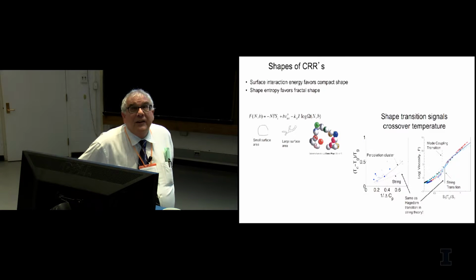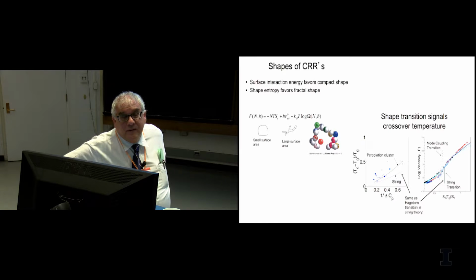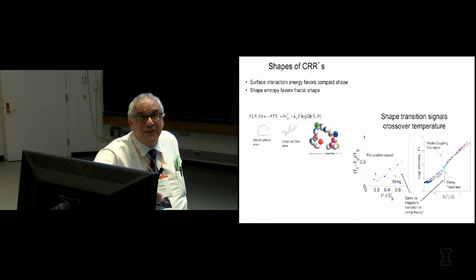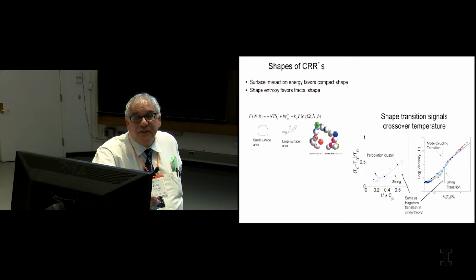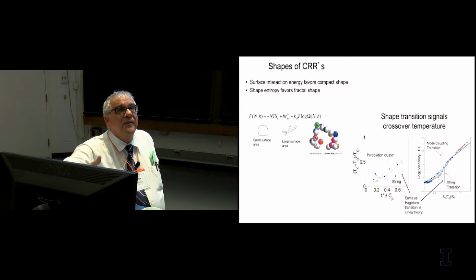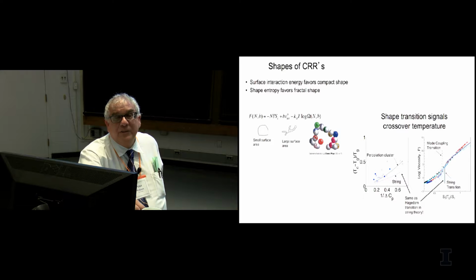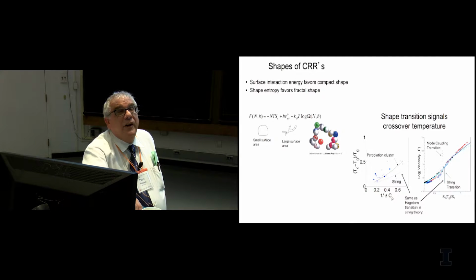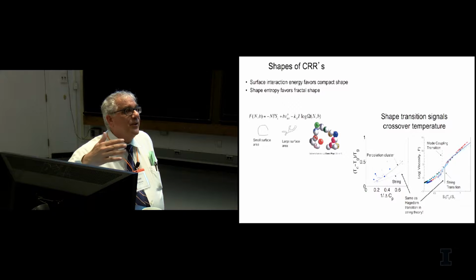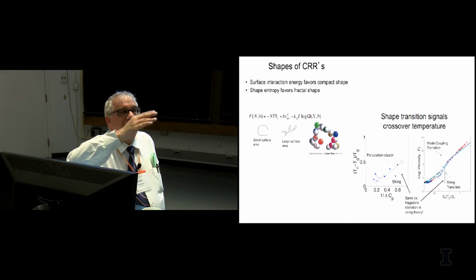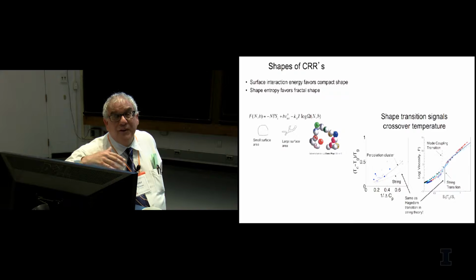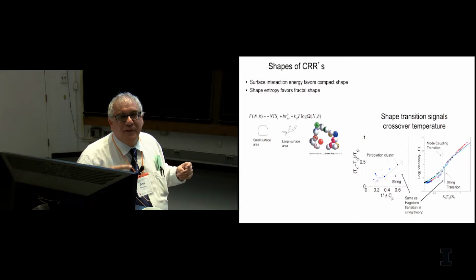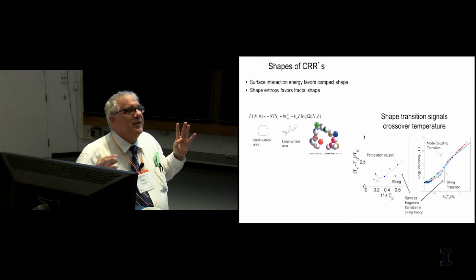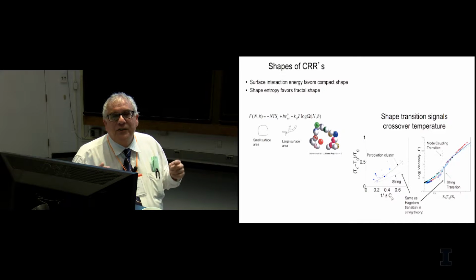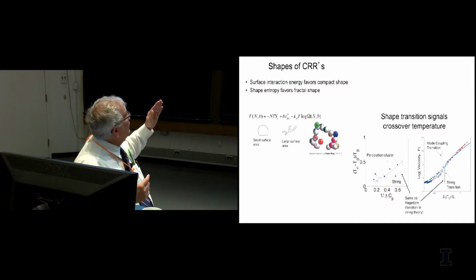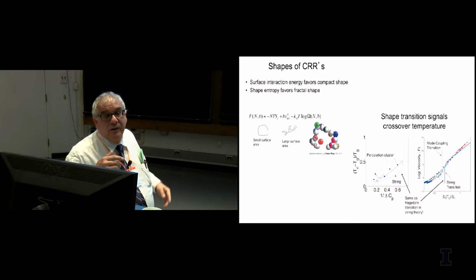One of the things is that there's kind of a no man's land between what goes on at these temperatures near the glass transition and the beginning of the ability to be trapped in the minimum. One of the reasons why it's hard to be trapped at the minimum at the high temperature is that if you make an object which is not a rough sphere as the region to reconfigure, but make it more varied and fractal in its shape, you get an additional entropic contribution,